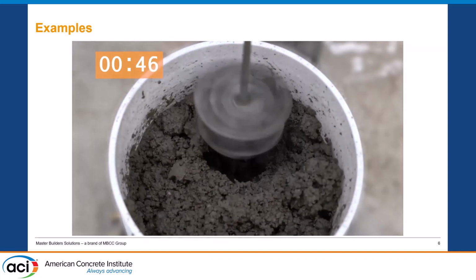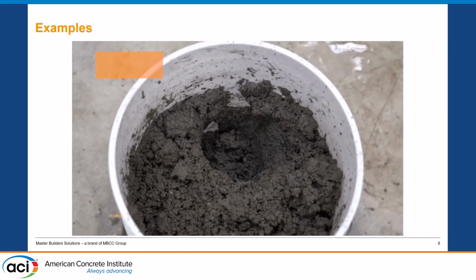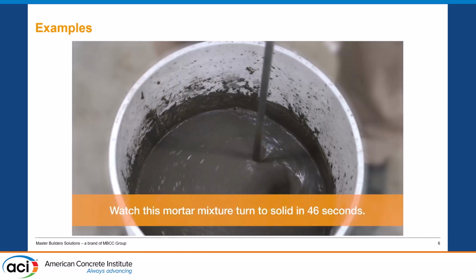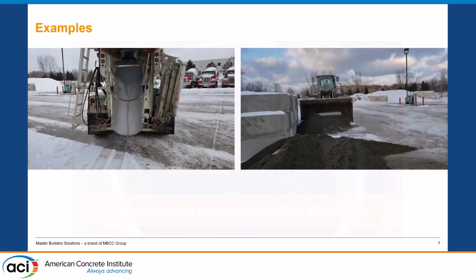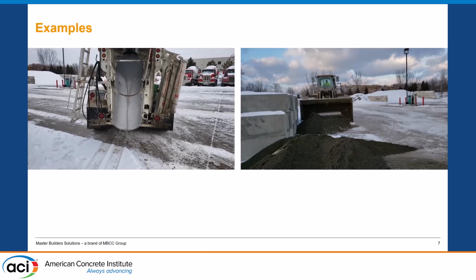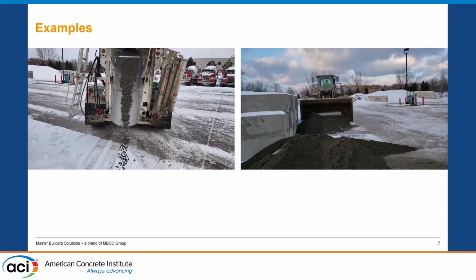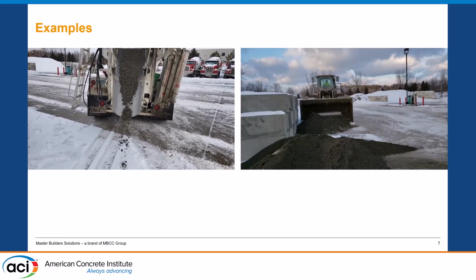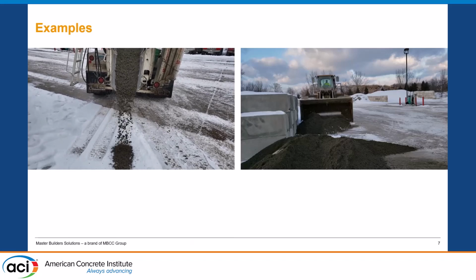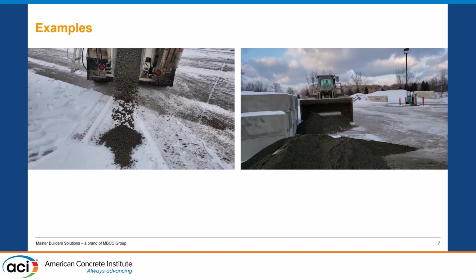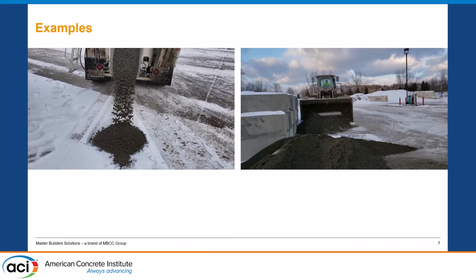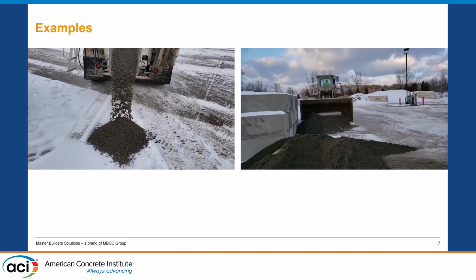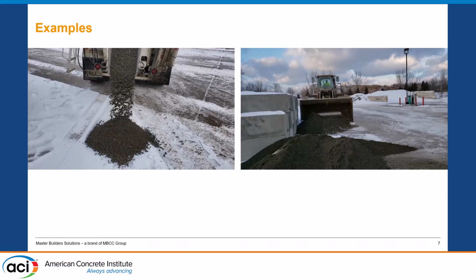Yeah, in a lab with a pedal mixer, that's simple. Why don't we look also in real life? So here we have an example of the same material being added to concrete. And after 2 minutes of mixing, you can just discharge the truck. This was 8-inch concrete that was treated. After 2 minutes, this is how it looks like. You can see the individual aggregates coming out of the chute.